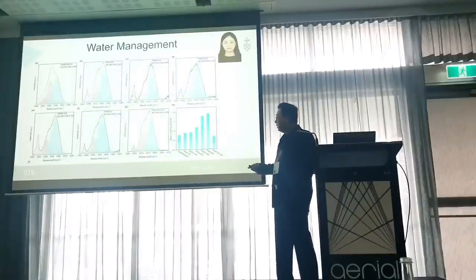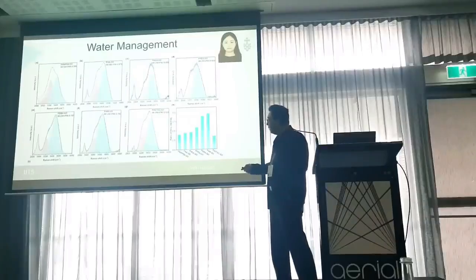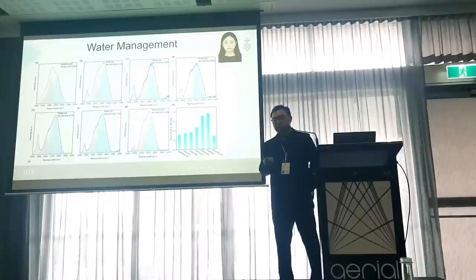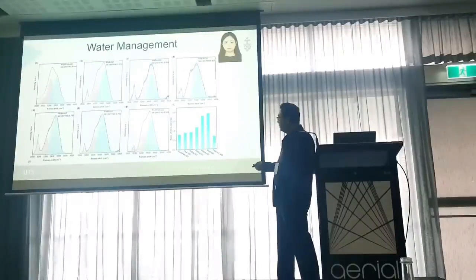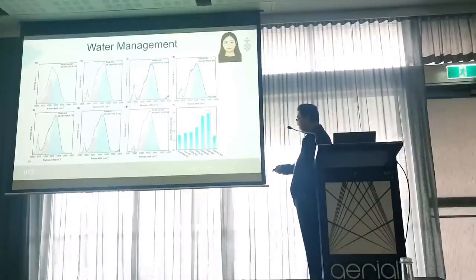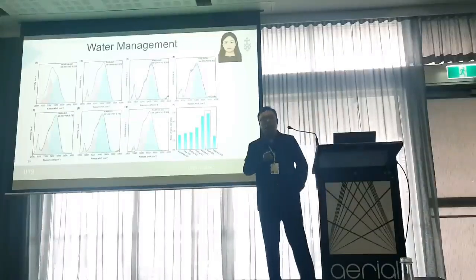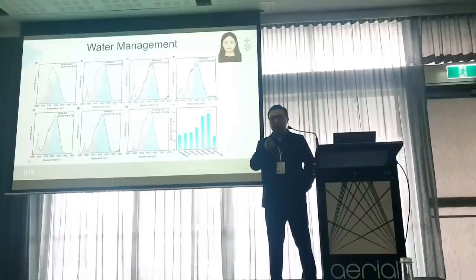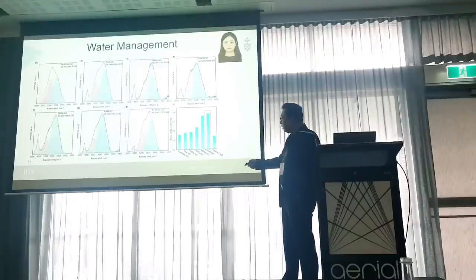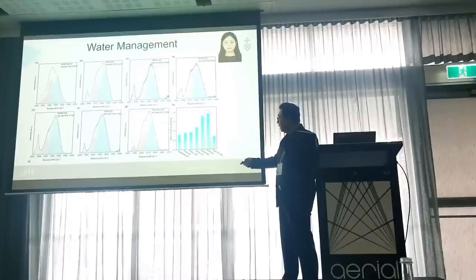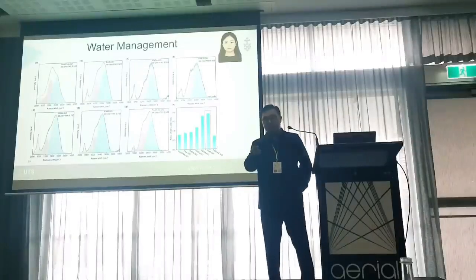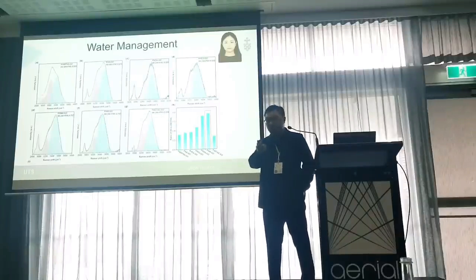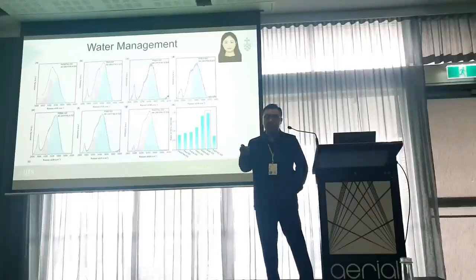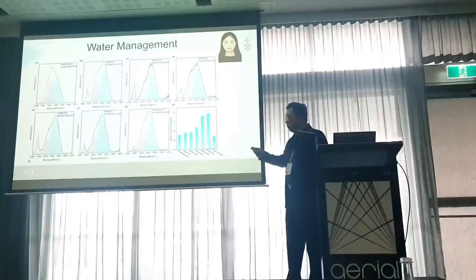So interestingly, we find that for this hydrogel, PN, with the amine group as the functional group, they show a higher intermediate water content. These results are summarized in this figure. As you can see, the PN hydrogels have the highest intermediate water content. The intermediate water is believed to be in a slightly excited state. That means the evaporation enthalpy of intermediate water is lower than that of free water. So if we have a higher intermediate water content, in this case about 78%, then 78% of the water inside the hydrogel is intermediate water, activated by the polymers. Therefore, under solar illumination, it can generate fast water evaporation.